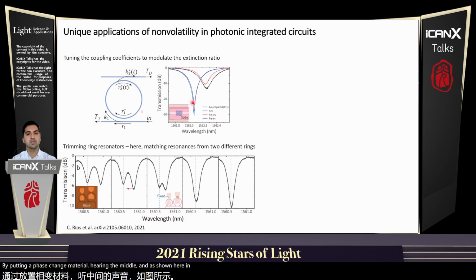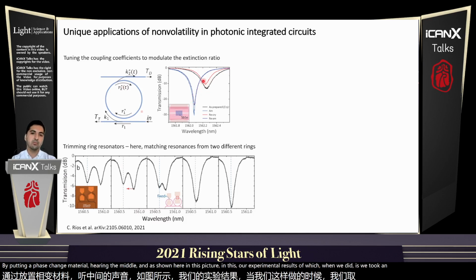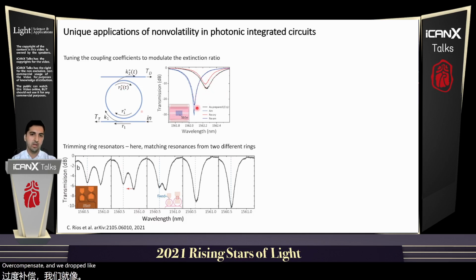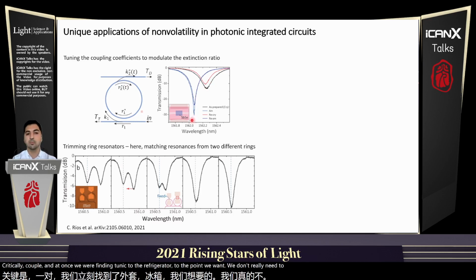And these are experimental results in which we took a ring resonator, here in the black line, that was originally overcoupled, and we were able to switch it and bring it to the point at which the ring is critically coupled. And once we fine-tune the ring resonator to the point we want, we don't really need to keep supplying power to leave it there.